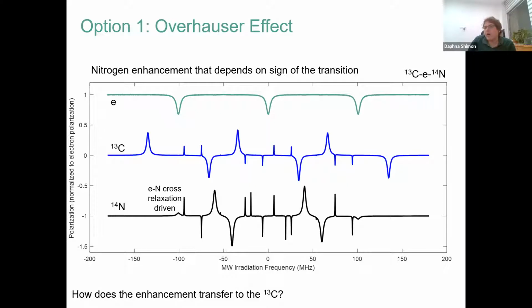And so I couldn't figure out how this actually works. And to me, it suggests that things like cross relaxation and dipolar couplings, which would be the things that transfer the polarization, aren't what's happening here, and that we're not seeing this Overhauser effect.